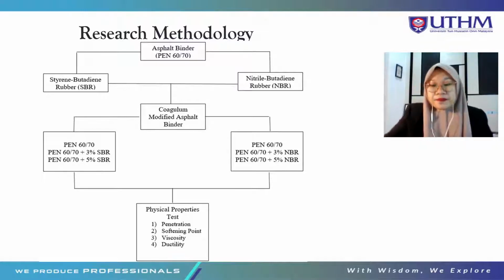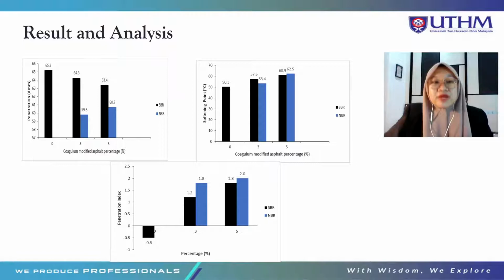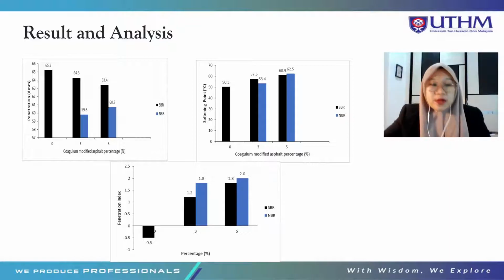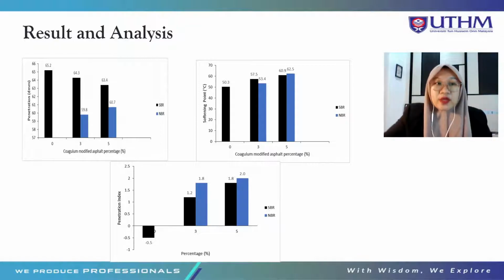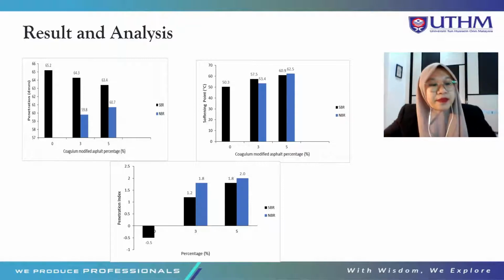This is the result and analysis part. The first figure shows the penetration value. The penetration value of SBR coagulum modified binder shows a different trend compared to NBR coagulum modified binder. The penetration values for the samples with 3% and 5% SBR were 64.3 dmm and 63.4 dmm. As the amount of SBR increased, the penetration value slightly decreased.